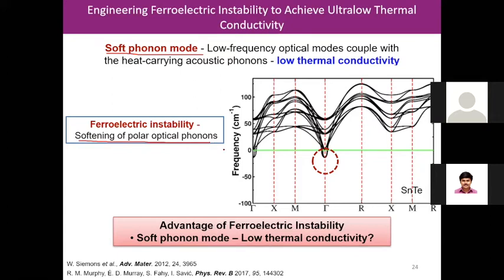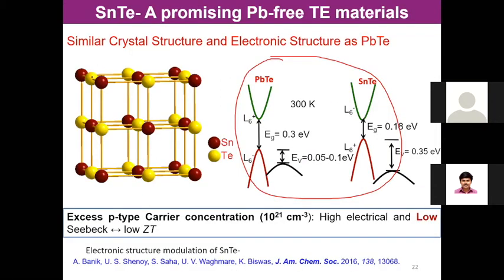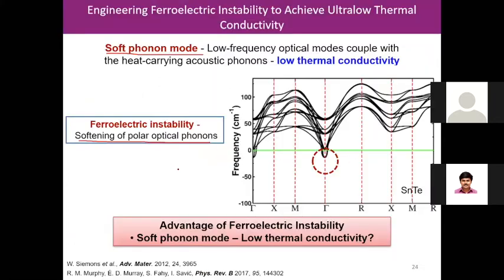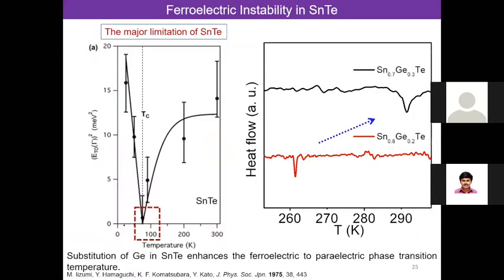Cubic tin telluride has this rock salt structure. I should tell you this rock salt structure is basically the sodium chloride structure, which is also the structure of lead telluride. This rock salt structure is stable at room temperature or above, but at very low temperature tin telluride forms a rhombohedral phase, which is non-centrosymmetric. That's why if you calculate the phonons of tin telluride in this rock salt phase, you see a very small optical phonon instability, and this is called the ferroelectric instability in tin telluride. There are papers published in the 1970s, even from Japan, which showed that there is a ferroelectric transition in tin telluride below 100 Kelvin.